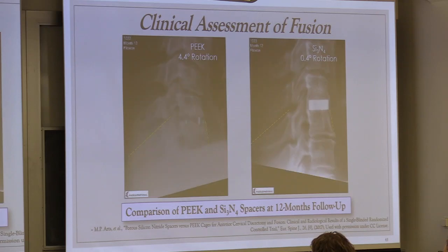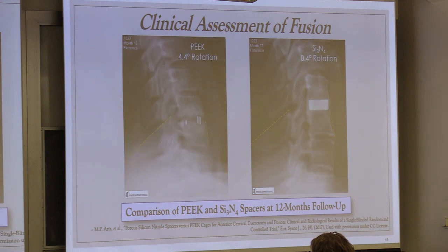More recently, a randomized controlled blinded clinical trial was conducted comparing PEEK and silicon nitride. I'll just show you one slide here. The outcome of the trial was what's called a non-inferiority trial. We wanted to just make sure that silicon nitride, in testing against a well-known device like PEEK, was non-inferior to PEEK, which the trial actually proved.